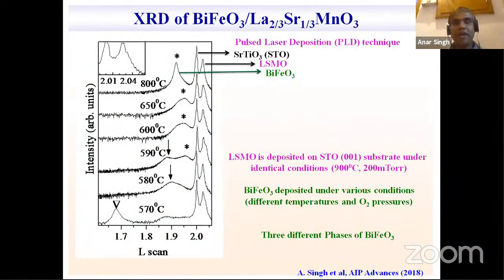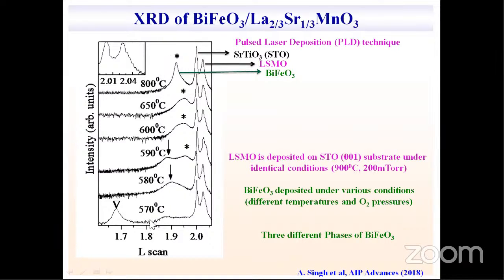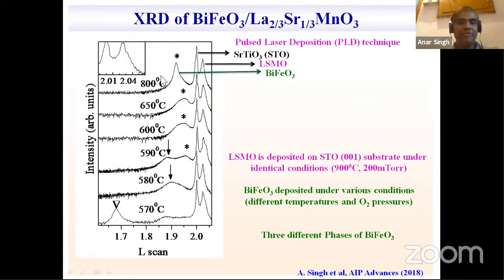So we have grown a BFO LSMO heterostructure using the pulsed laser deposition technique. This is the XRD pattern of the heterostructure. The strongest peak corresponds to the substrate, which is SrTiO3, on which the films were deposited. The peak on the right-hand side of the strongest peak is the peak of LSMO. And at lower 2 theta, the lower L value, this peak marked with a star corresponds to the bismuth ferrite 002 type reflection. And the films were deposited at various temperatures in different oxygen pressure.